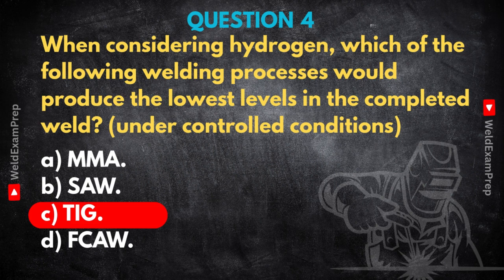TIG. Okay, that makes intuitive sense and often seems like a cleaner process. But what specifically about TIG keeps the hydrogen down compared to, say, MMA or SAW? The key difference is the absence of flux. In MMA, you have the electrode coating. In SAW, you have granular flux. In FCAW, you have flux inside the wire. And flux can hold moisture. Precisely. Moisture, H2O, is the primary source of hydrogen in welding. Fluxes, especially if not stored correctly or baked properly, can absorb moisture from the air. When that moisture hits the arc, it breaks down and the hydrogen dissolves into the molten weld pool.